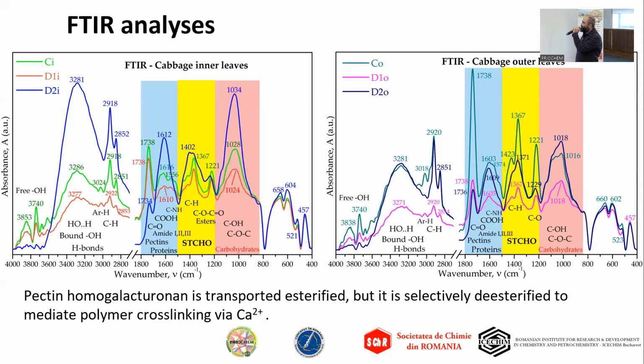If we compare now the control with the two dosages, we can see in the free hydroxyl bonds that the signals decrease, which suggests fewer free hydroxyls, and the bound hydroxyls increase, which suggests carbohydrates accumulation and more hydrogen bonds involved in stabilizing and biofortifying the structure. Also, the signals around 2900 correspond to carbon-hydrogen bonds in aliphatic structures, due to their sharp shape.